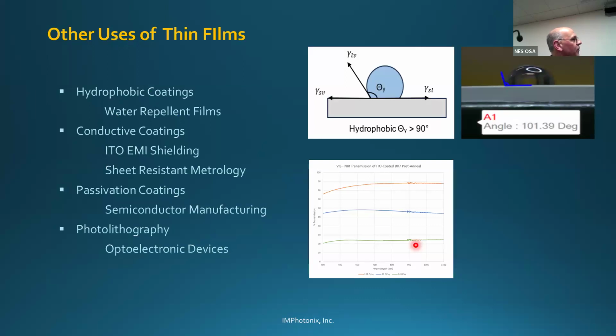These are some of the other uses of thin films that are kind of related to the optics industry. So we also, in the industry, have been working a lot with hydrophobic coatings, and these are coatings that are more used for humid environments where you want the moisture to actually run off the coating. These hydrophobic coatings are measured by applying a drop and looking at the contact angle that drop makes with the surface. For coatings that are not hydrophobic, the drop will tend to spread out onto that surface.